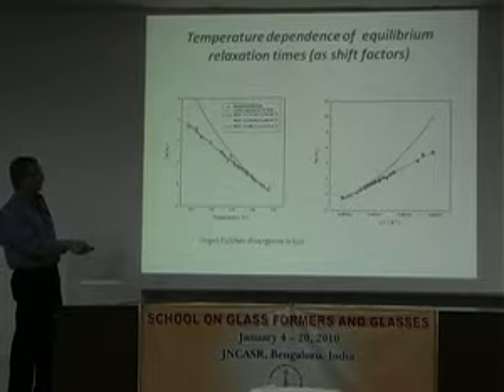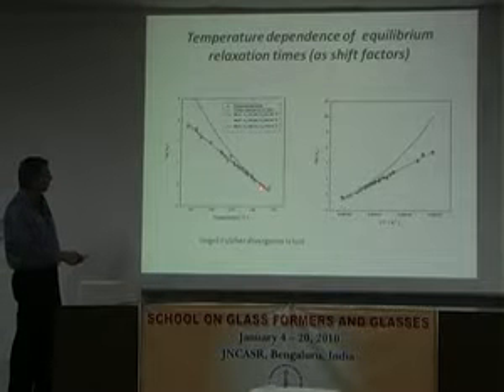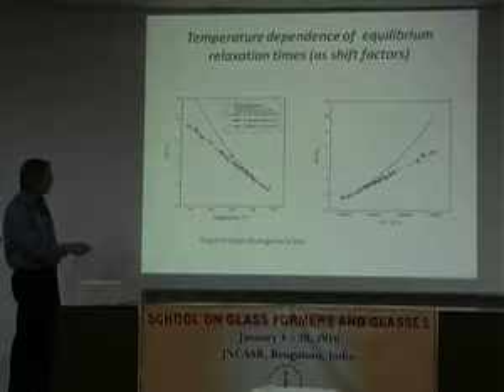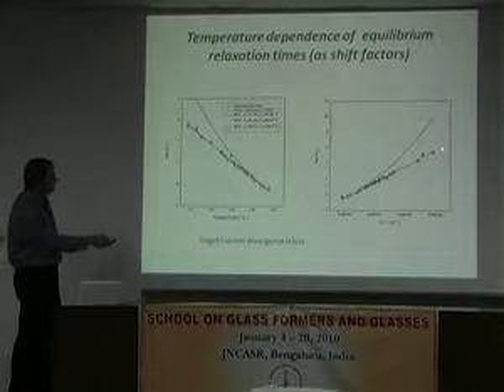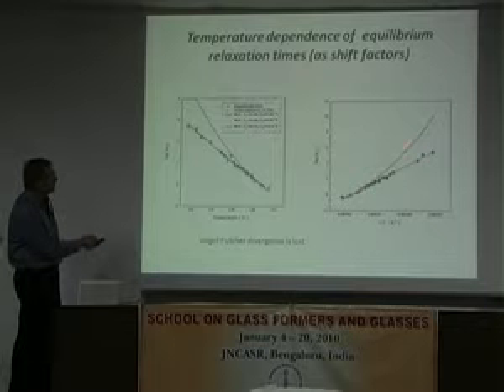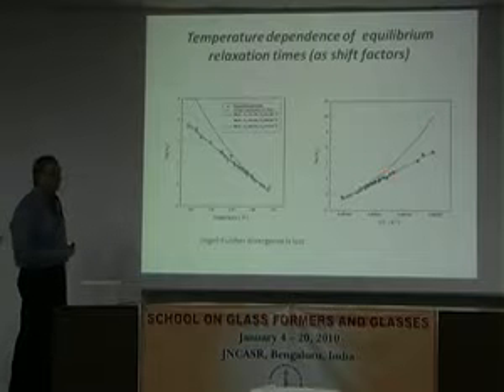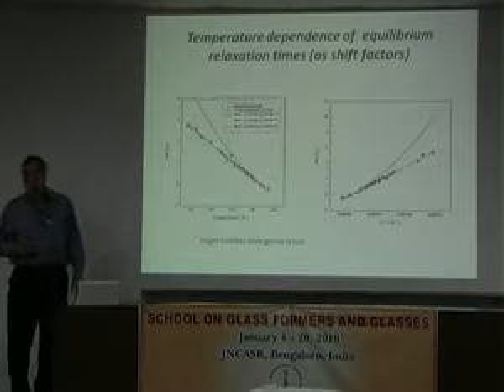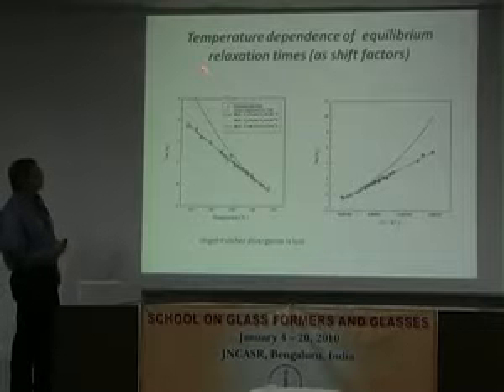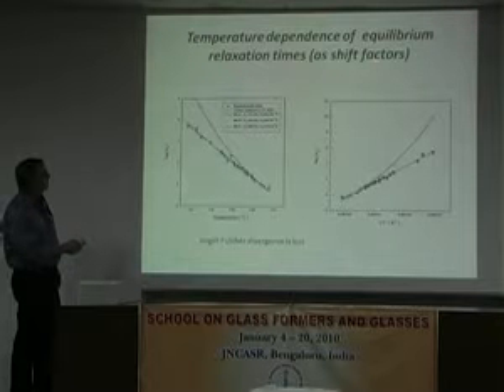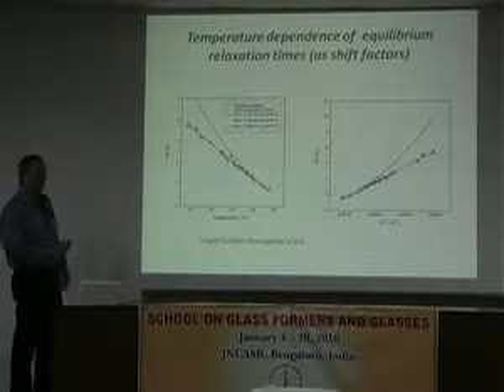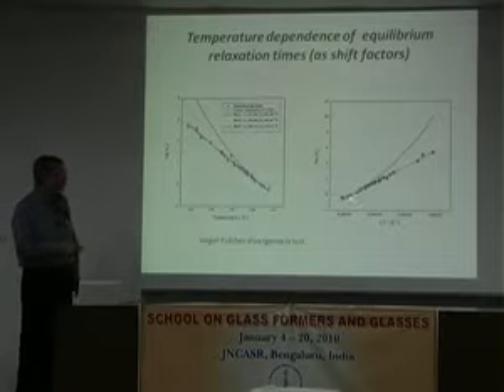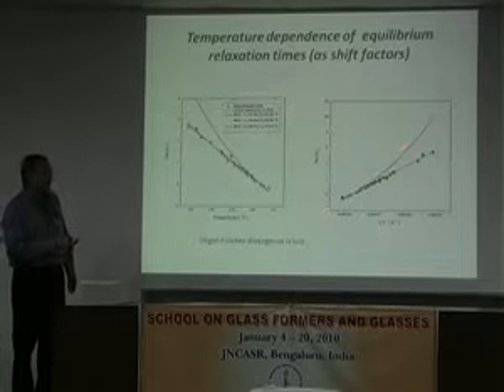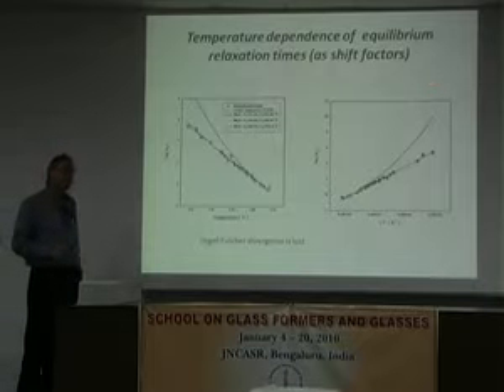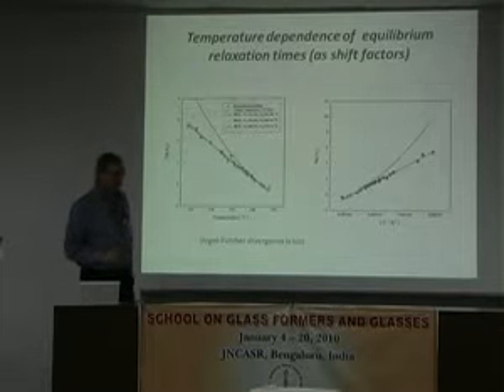Here's the Arrhenius type plot, so you can see where we're limited enough in temperature range that it doesn't make any difference. This is the equilibrium line. This is the extrapolated Vogel-Fulcher behavior for that material. So what we see is, at least, the equilibrium relaxation times as shift factors, or if you like, as reduced relaxation times, do not follow this diverging curve.